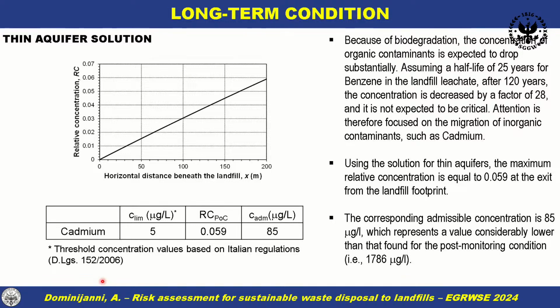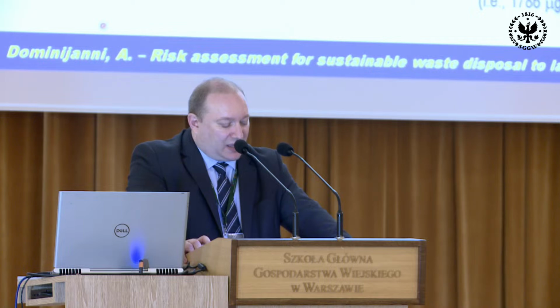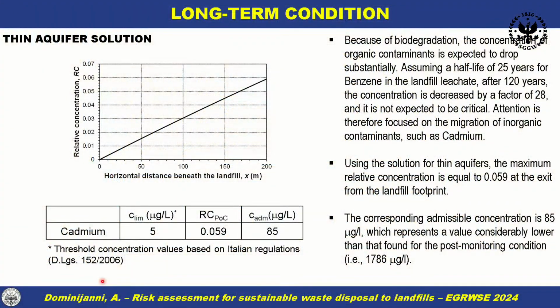Because of biodegradation, the concentration of organic contaminants is expected to drop substantially. Attention is therefore focused only on the migration of inorganic contaminants, such as cadmium. Using the solution for thin aquifer, the maximum relative concentration is found to be equal to 0.059 at the exit from the landfill footprint. The corresponding admissible concentration in the waste leachate is 85 micrograms per liter, which is a value considerably lower than the value of 1,786 micrograms per liter found for the post-monitoring condition.